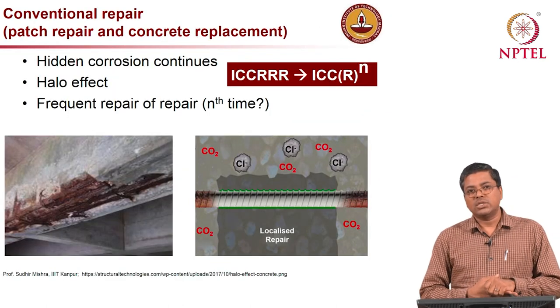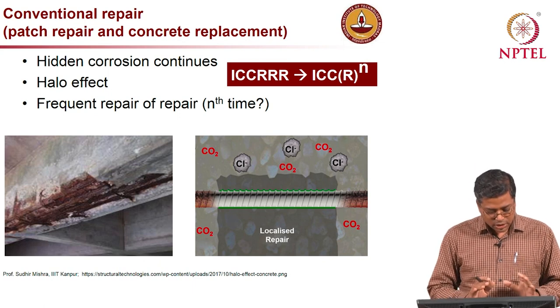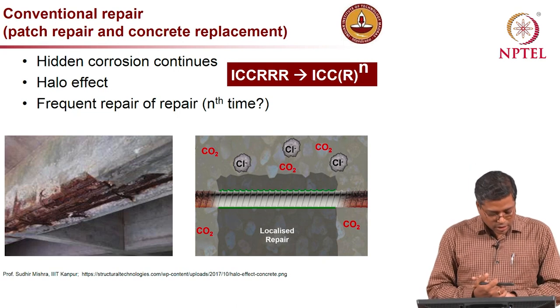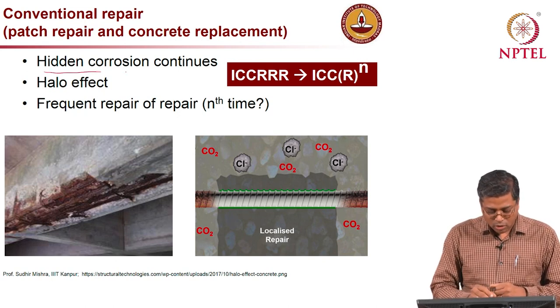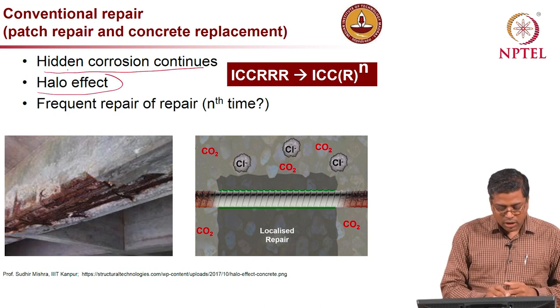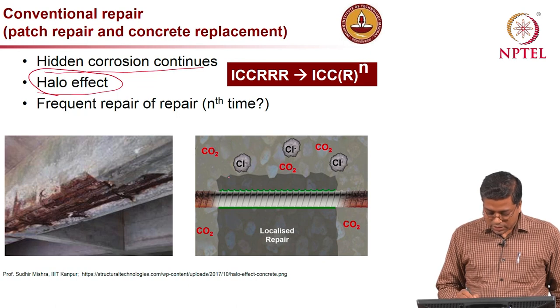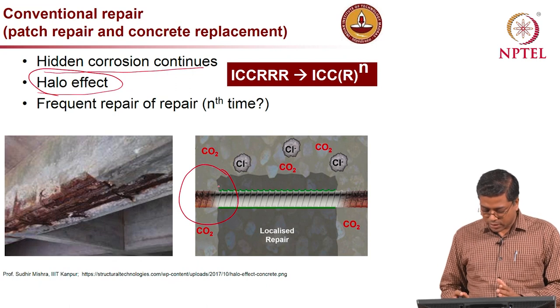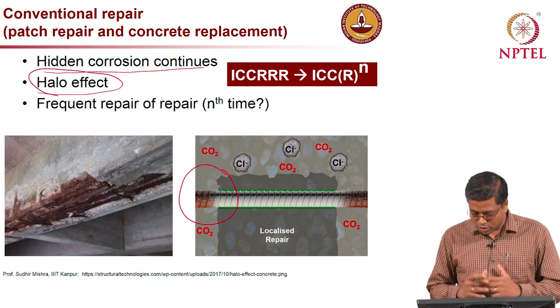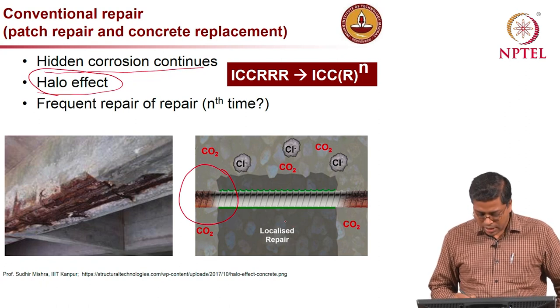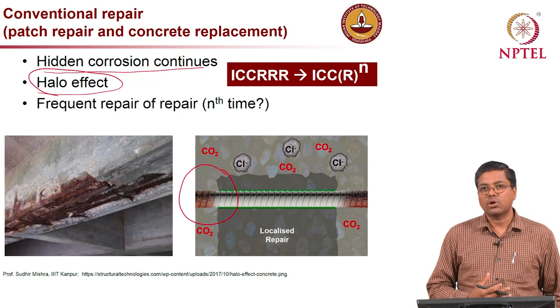In conventional repair of heavily corroded rebars, we clean the rebar, apply coating, and then do patch repair. However, a phenomenon called the halo effect occurs: the new repair material is good quality concrete, but the surrounding old concrete still contains carbonation or chlorides, creating a different chemical environment.